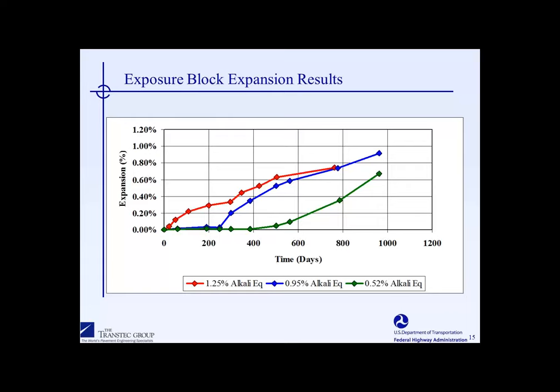All of these blocks were measured as a function of time for expansion, and you can see that on this next graph. With this graph, you can see that the highest alkali mix started to expand first, followed by the 0.95% alkali mix, and lastly, the low alkali mix began to expand after about a year or so. But ultimately, over the course of, say, 3 years or so, they all expanded considerably, well above 0.6%. This is the way that our research group tends to evaluate concrete mixes for alkali thresholds, by casting these large blocks where leaching will be very minimal because of the large size of the blocks themselves.